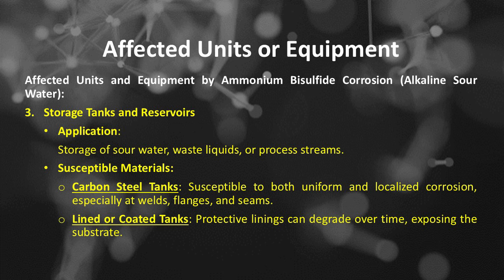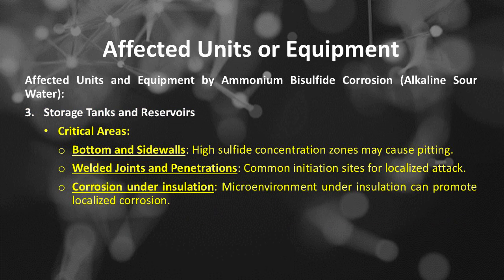Affected units and equipment by ammonium bisulfide corrosion or alkaline sour water. Number 3 is storage tanks and reservoirs. The application of storage tanks and reservoirs is storage of sour water, waste liquids, or process streams. The susceptible materials include carbon steel tanks, susceptible to both uniform and localized corrosion, especially at welds, flanges, and seams. Lined or coated tanks: protective linings can degrade over time, exposing the substrate. The critical areas include bottom and sidewalls.